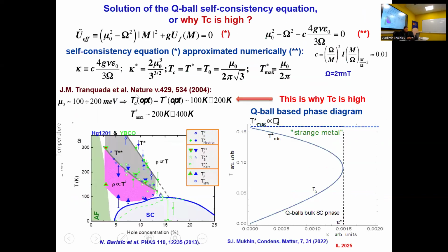But I should go further fast. So it is possible to find out the dependence of T star and Tc as function of the coupling strength, which is G nu epsilon 0 divided by omega star. And then we can find out the absolute values of temperatures on this branch, which we call strange metal region, and this branch, which is the bulk superconducting phase.